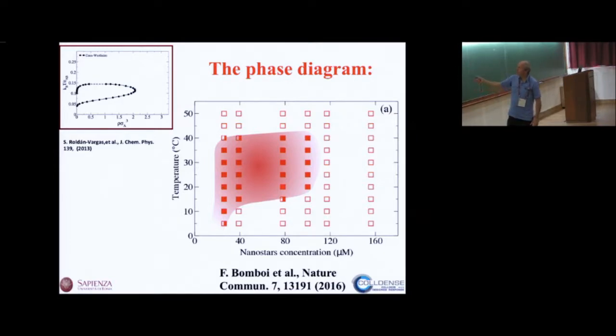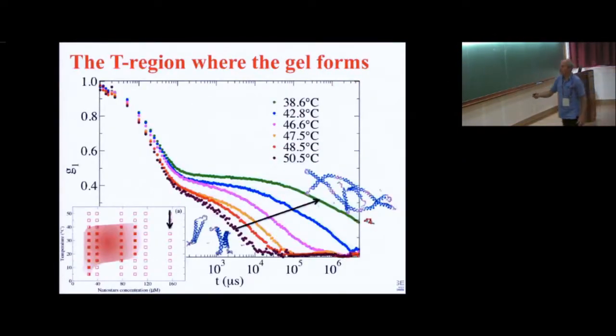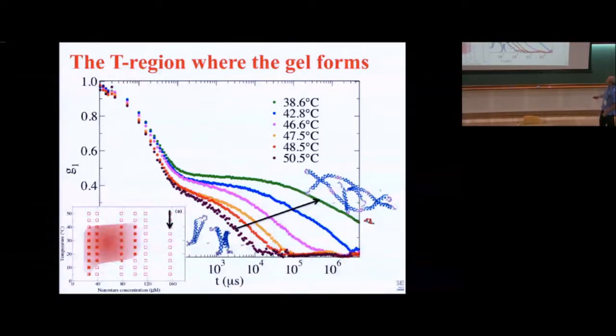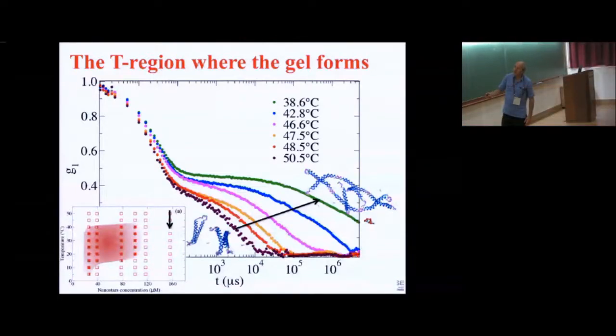Now we can go in at this density over here, where the system is not phase separated. It's a perfect equilibrium gel. And we can cool it down. We start to go from high temperature to low temperature. And you see that the alpha relaxation time gets slower and slower, and the system goes above 10 seconds. Again, you cannot do experiments anymore. So for us, it's non-ergodic. So it's really a gel. And if you keep cooling down, you cannot do experiments. The correlation function does not decay in your experimental time window.